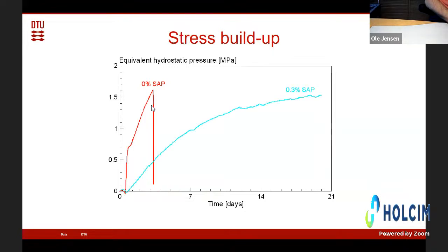If we, on the other hand, add 0.3% of superabsorbent polymers relative to cement weight, stresses develop much slower and no cracks form. And if we add 0.6% SAP, we can almost eliminate the stress buildup. So for each kilogram of cement, just add a spoonful of SAP, and you very considerably change the behavior of the concrete. It is mind-boggling.